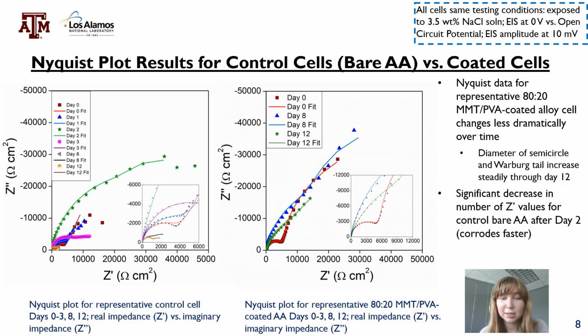What is meant by this is that from day 0 to day 12, there is a steady increase in the diameter of the semicircle, giving way to a larger Warburg tail. However, if you take a look at the bare aluminum alloy control cell on the left-hand side, there is a dramatic jump in the amount of Z prime data points from day 1 to day 2. In addition to this, after day 2, there's a great decrease in the size of the Warburg tail, giving way to a smaller number of Z prime data points.